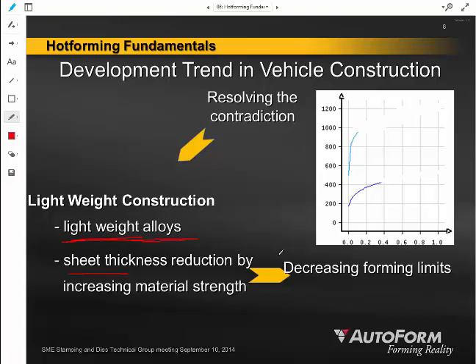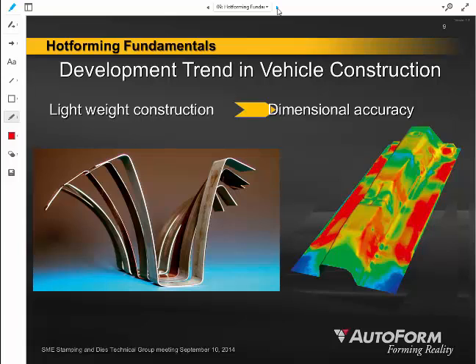However, it's going to also mean that that material is going to inherently want to avoid the deformation that we might be trying to apply in a sheet metal stamping die. Right? And you can't necessarily have it both ways. Can you have a material that resists undesirable deformation but accepts what we think of as desirable deformation? And generally, I have to say, well, no, the material cannot tell the difference between what is desirable deformation and undesirable deformation. Hot forming and hot stamping is a way around that, because heating that material up is a way that we're differentiating the desirable deformation that we're doing in the hot stamping operation from the undesirable deformation, which would be the deformation in ambient temperature of a vehicle in crash.